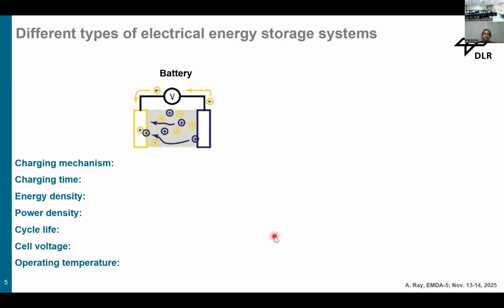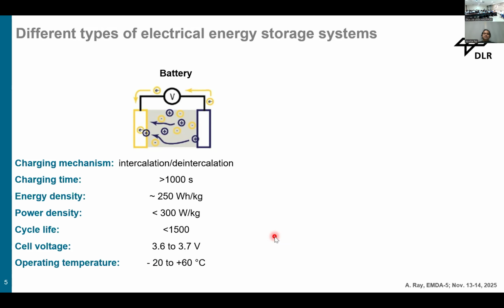The main property of lithium batteries is the charge-discharge mechanism. The charge-discharge mechanism is intercalation and deintercalation of the ions. That means the ions can intercalate into the electrode material and also come out from the electrode material. So that is the main reason a lithium-ion battery takes longer to fully charge, and it can also discharge for a long time, because it needs a long time to intercalate and deintercalate the ions from the electrode materials. So its charging time is very high, a few minutes to hours.